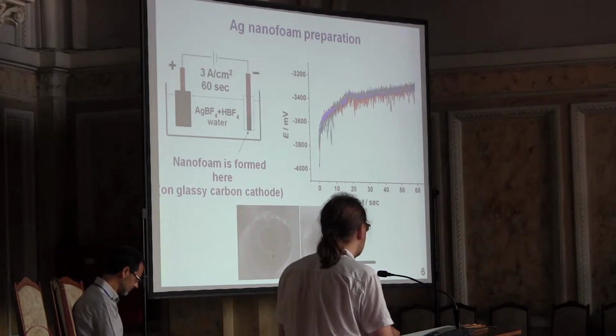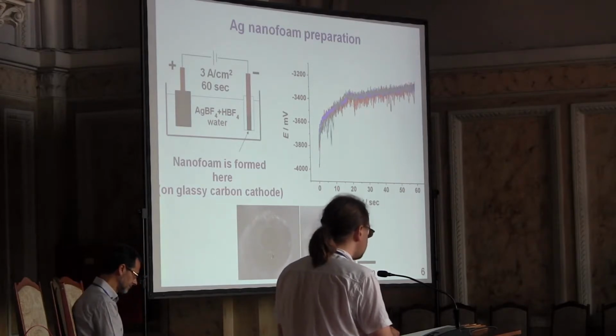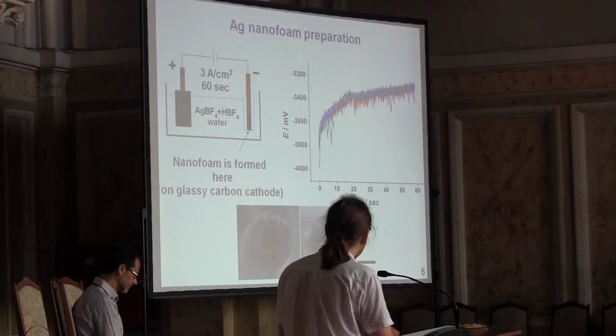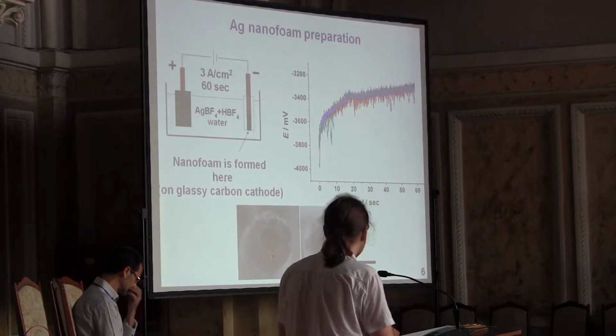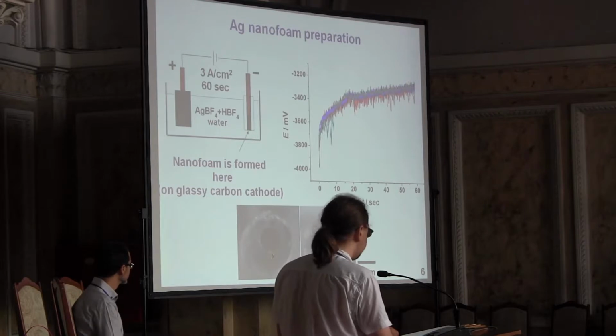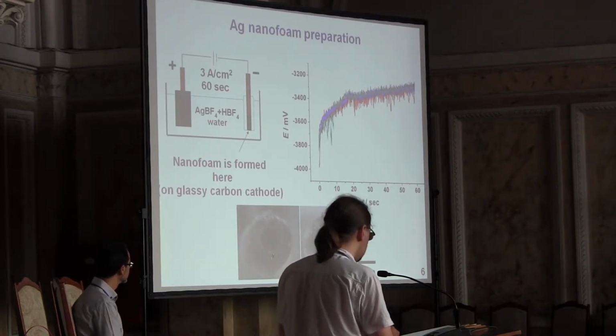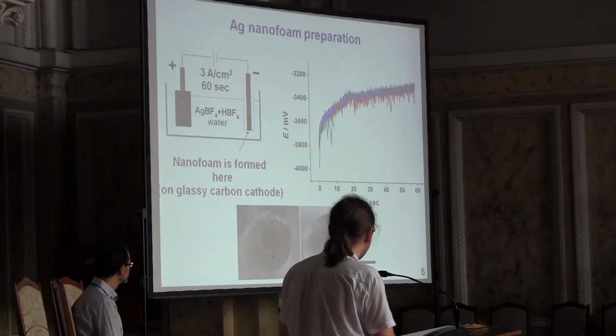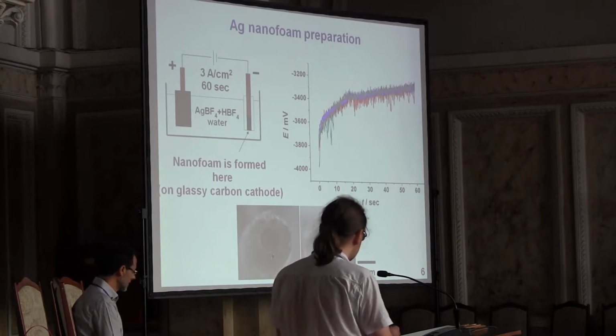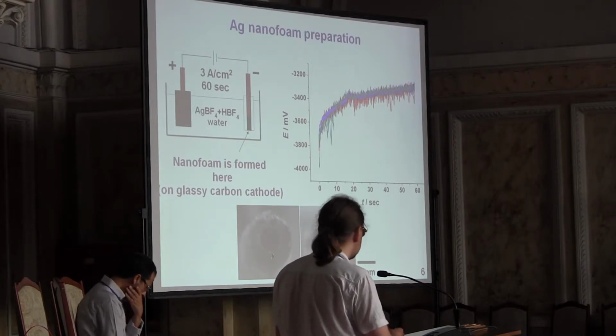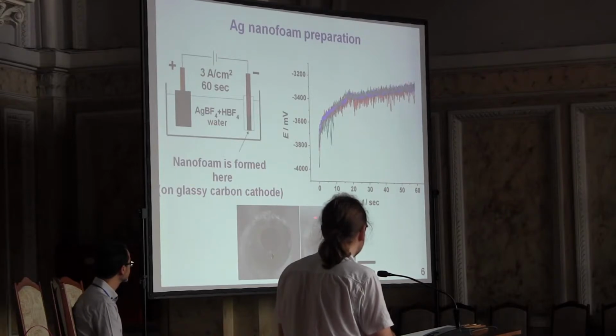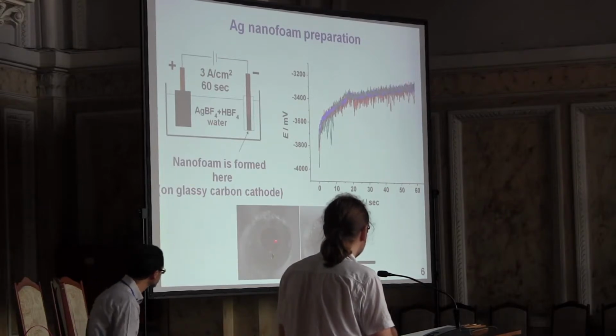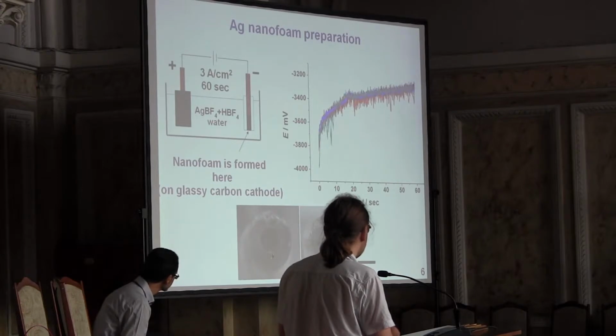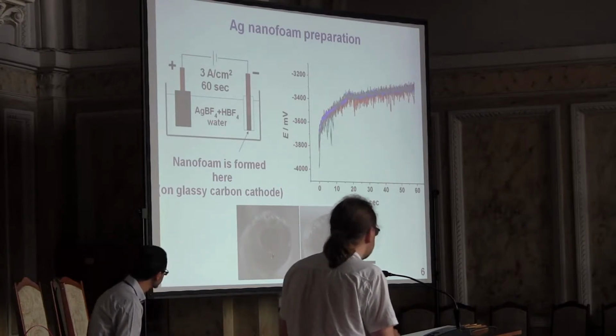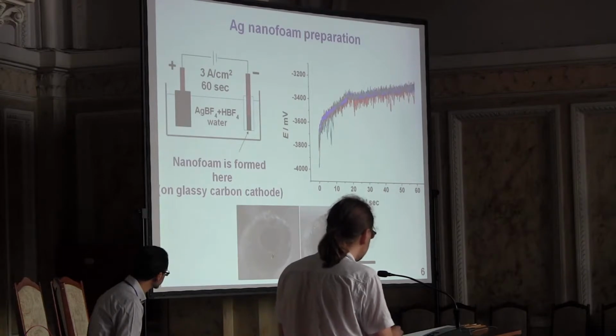Silver nanofoam for this work was prepared using typical method of cathodic electrodeposition. However, we tried to optimize the composition of electrolyte used for this process. We tried to simplify it as much as possible. The nanofoam coating was formed on the surface of glassy carbon electrode as matte gray film. The chronopotentiograms of the formation processes